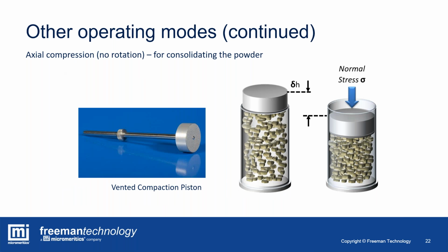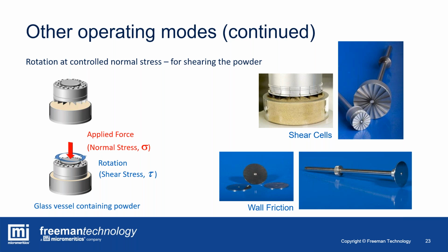And we also have what we call a shear cell accessory. I'm sure many of you are familiar with these types of methods, but simply it's a quasi-static measurement in contrast to the dynamic measurement. So this is about the onset of flow at very low shear rates, and it's a measurement under consolidated conditions. So here, there's an applied normal stress or force, and then whilst that's being controlled, rotation occurs and the powder slowly begins to shear, resulting in an incipient failure or the yield point of the powder bed. And by plotting the relationship between shear stress and normal stress, you can derive the yield loci and various other parameters that relate to flow behavior of the material, particularly good for understanding behavior in bins and silos.